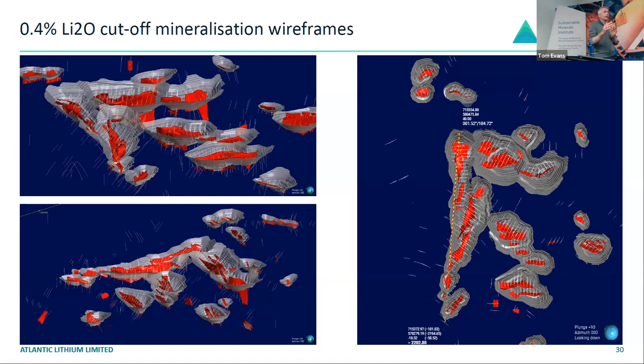Notwithstanding, you need a highly fractionated LCT pegmatite. So that's one aspect. But once you do even have one of those fractionated pegmatites, what is the mineralogy? What is the grain size? What is the hardness of the pegmatite? That also drives the processability. You see, the hardness drives how many fines you generate through that primary crushing phase. And the higher amount of fines you generate through the crushing stage can dictate whether or not you need to go down a flotation flow sheet, even though you may have coarse spodumene. So this is the case in Pilgangoora. It has a high work index and accordingly generates a high proportion of fines through that primary crushing phase.